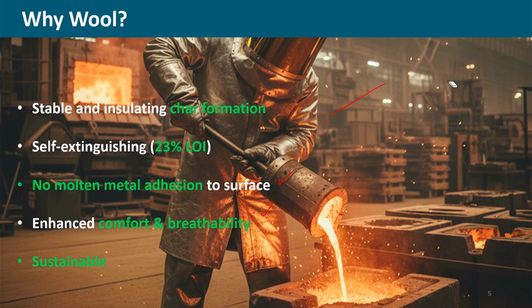It forms insulating char, which enhances the thermal insulation, and which is stable in nature; it does not change. Self extinguishing, it does not burn on its own. Molten metal adhesion is not there. So, when molten metal drops, it can shed out immediately. It is comfortable and breathable because of the structure, because it is hydrophilic in nature, with moisture absorption, and being a natural resource, it is sustainable. So, with all these advantages, we have selected wool as one of the components.